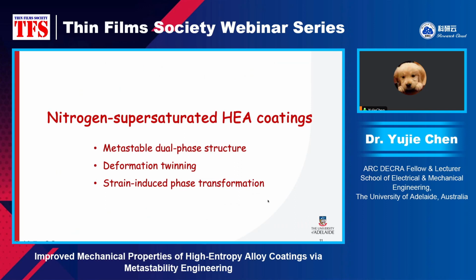Normally, to apply metastability engineering in high-entropy alloys, the phase stability is tuned by adjusting the concentration of metallic alloying elements, like the example I showed in the previous slides. Another way to tune the phase stability is to add interstitial elements, but normally at very low concentration. We will talk about this later. However, in our work, we added a large amount of interstitial nitrogen to tailor the phase stability. The reason for doing that is that the phase metastability will give us dual phase structure, deformation twinning, and phase transformation. And in addition to all these benefits, we will also benefit from the massive solid solution strengthening caused by high nitrogen intake.